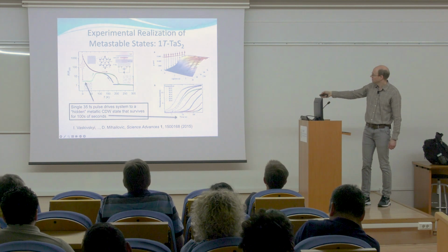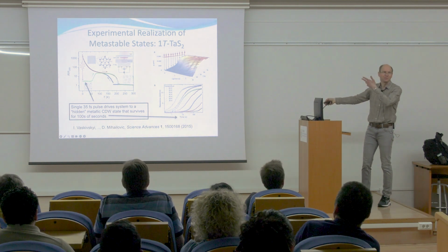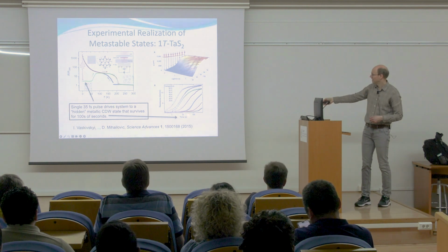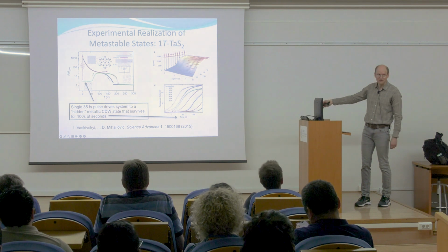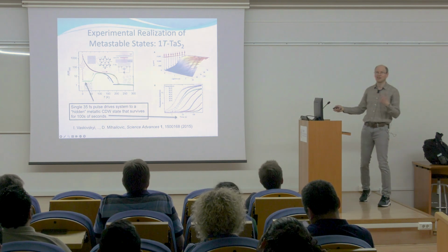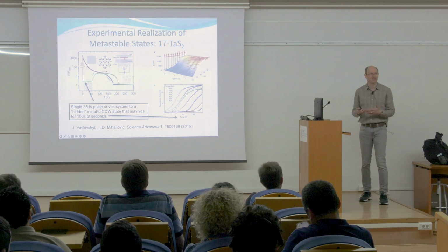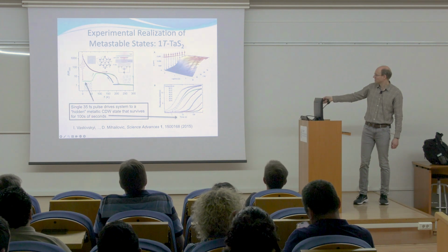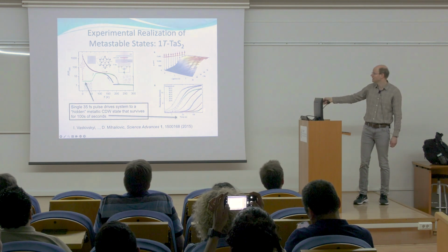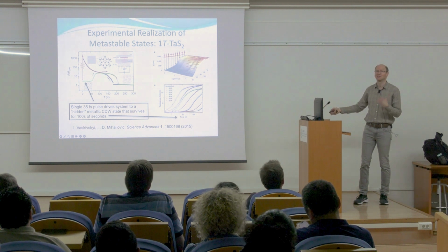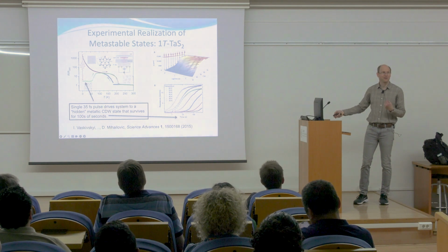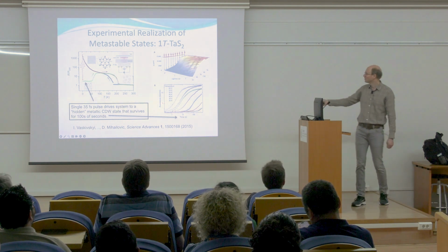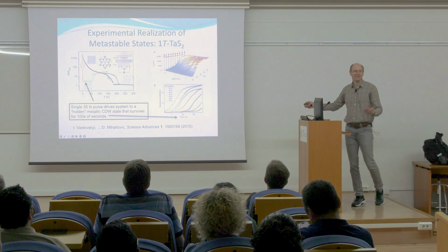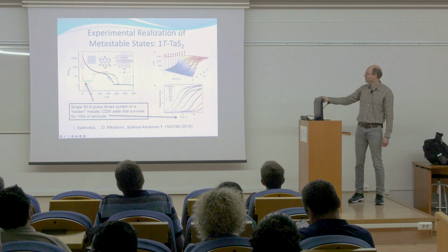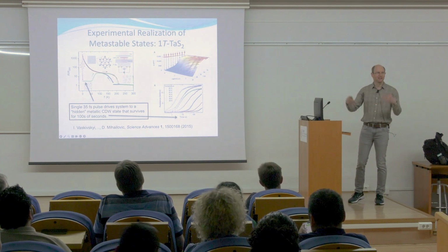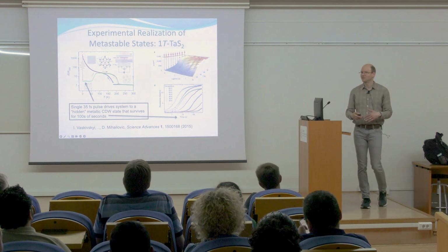And here's the plot showing how the resistance recovers, comes out of this metastable state as a function of time. Notice the time scale here is in seconds. I mentioned that femtoseconds is the characteristic time scale of electron relaxation, etc. So you can see here, this is like 100 seconds or 200, or 2 minutes. So this is like 17 orders of magnitude longer than the characteristic time scale of femtoseconds. This is an eternity from the point of view of the electrons. So you have an effectively eternal state, from the point of view of the quantum motions of the electrons, of this low resistance, new hidden charge density wave state, which has been induced by just one pulse of light.